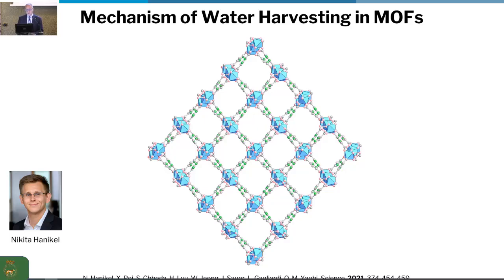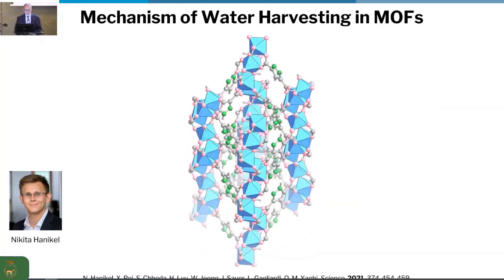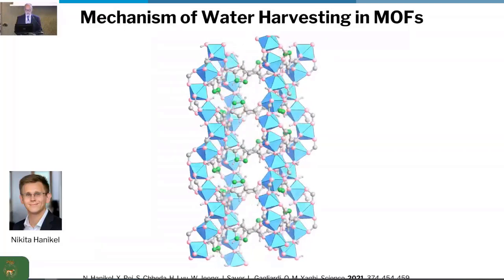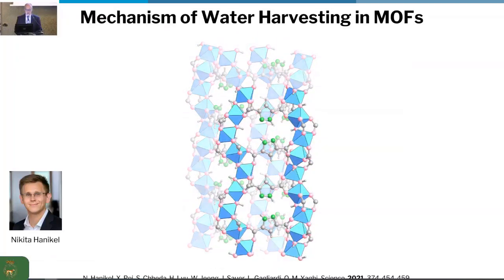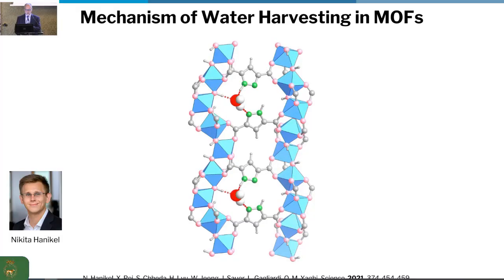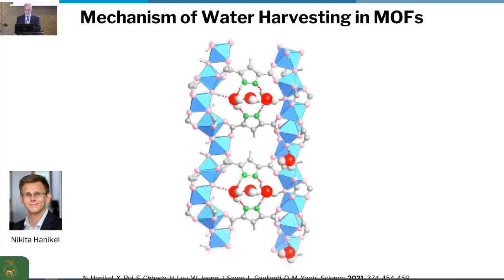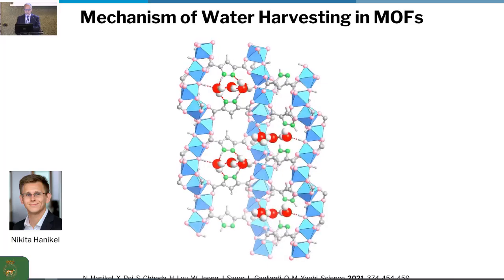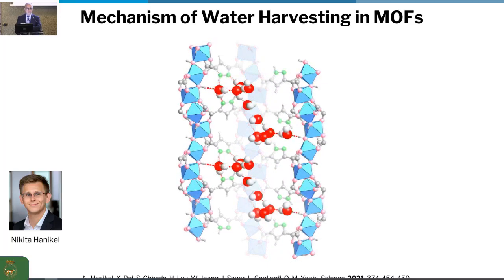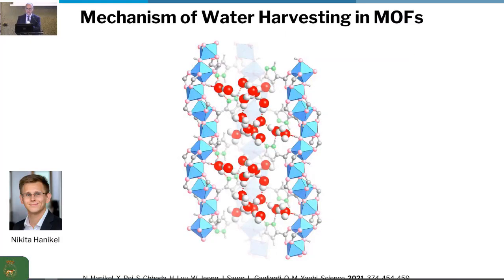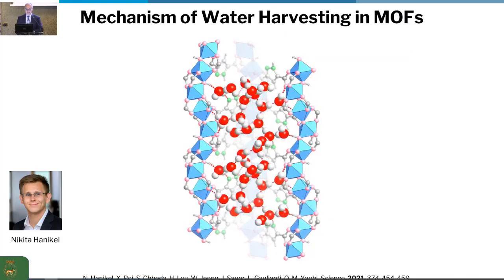So Laura got the exact location of the most important water molecules in the pore correctly. And that should make a believer out of all of us in computational chemistry. So here, I'm going to excise one pore out and slice it to show you exactly where each water molecule goes. It goes first to the hydrophilic sites. That's 4 waters go into the hydrophilic sites, and then as the hydrophilic sites get filled up, it bridges over the hydrophobic sites, thereby filling up the pores.